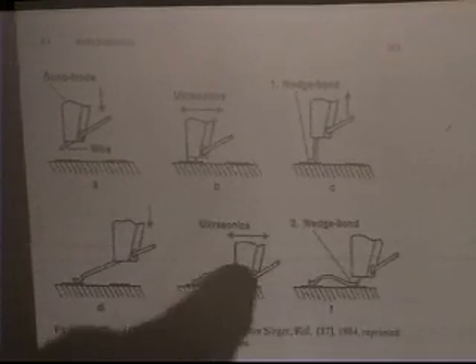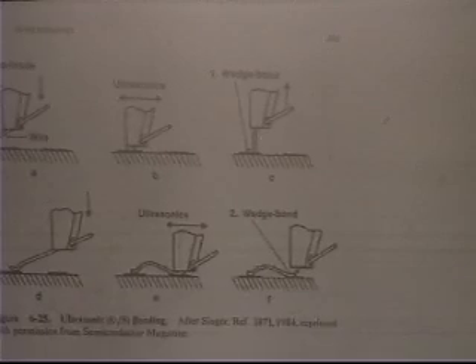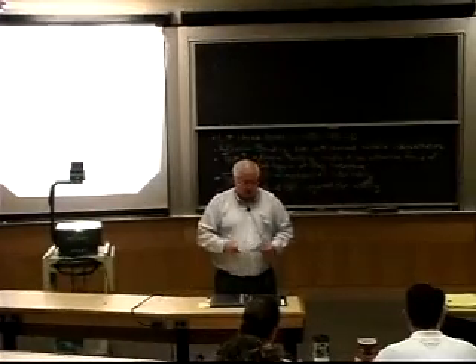I also found some of my overheads that we talked about on wire bonding, and I talked about a little sewing machine needle. This is ultrasonic wire bonding, with a head which they call a sonotrode because of the ultrasonic vibration to help the wire bonding. It's basically a little metallic needle, if you will, with the wire fed through it, and it comes down. Apply ultrasonics in this case, and you end up making a wire bond on a pad here, and then it comes over and makes another one. They can only make about 7 a second of these bonds. So this thing's humming along pretty fast, and basically it's limited by the inertia of the system. You just can't move that mass much faster and still have precision. You start getting all kinds of dynamics.